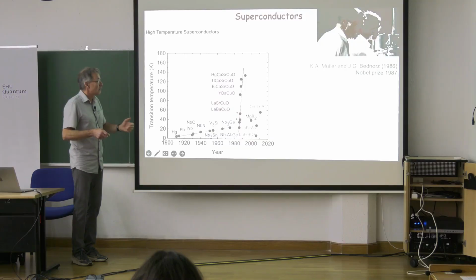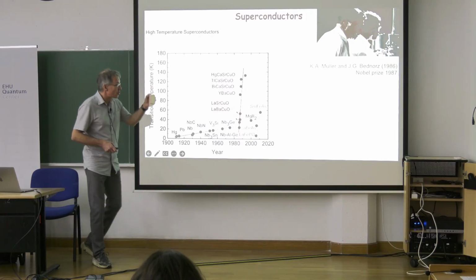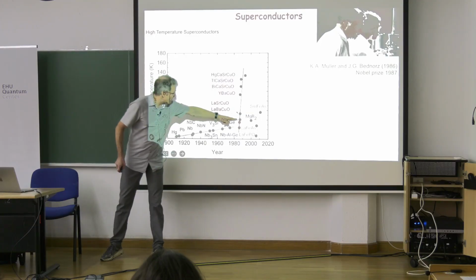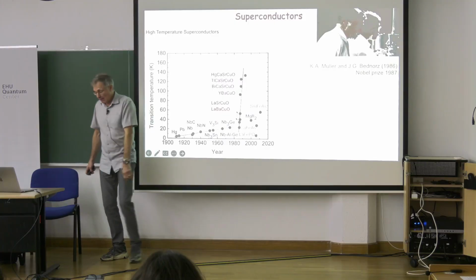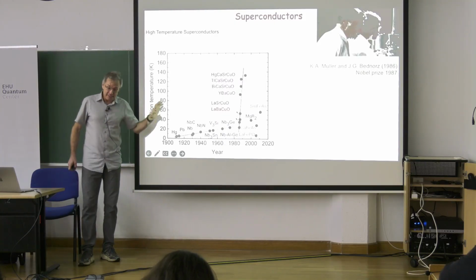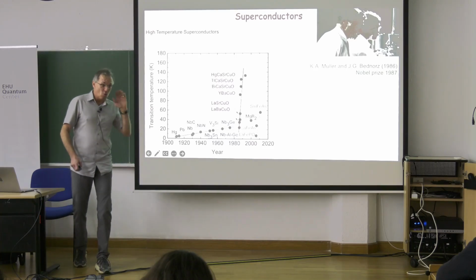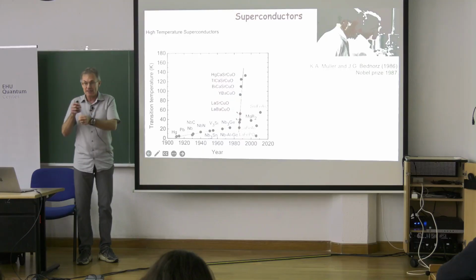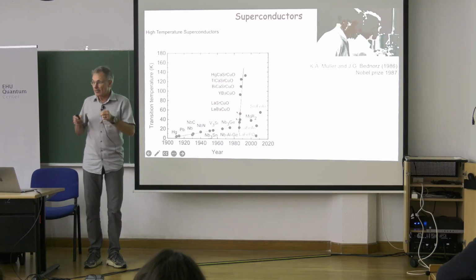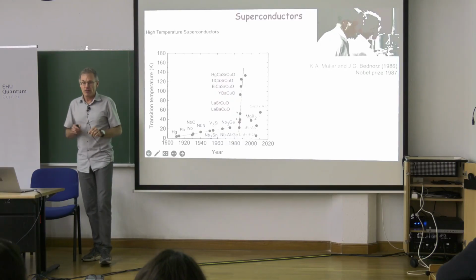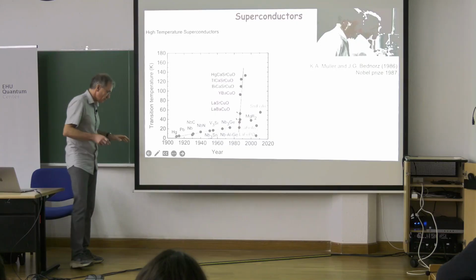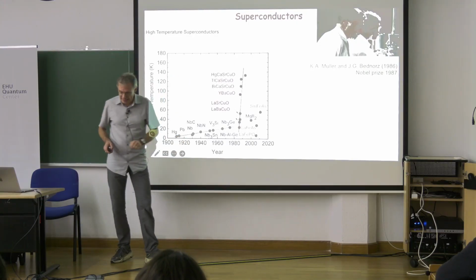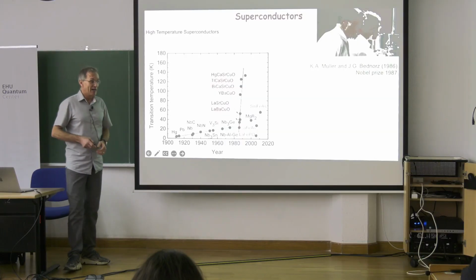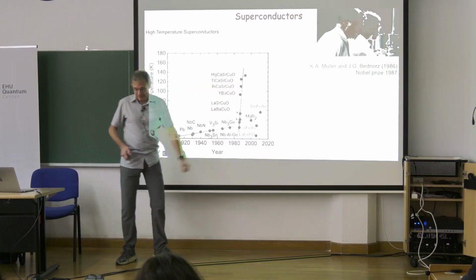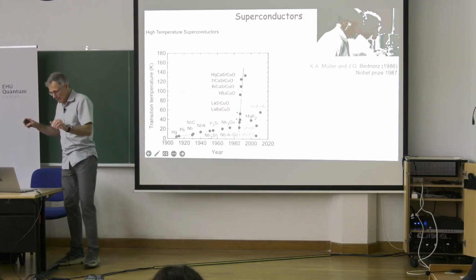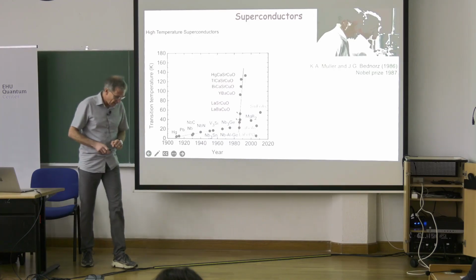And this was a huge surprise when Alex Müller and Georg Bednorz discovered, actually what they discovered was a little bit higher, at 36 Kelvin, a lanthanum compound. Well, they didn't discover it by chance. Alex Müller had studied for decades and tried to find high temperature superconductivity, and he had his own ideas where to look. Most people believed that the ideas were wrong, that he was looking for a black cat in a dark room where the cat was not there, but he found it. It was a huge rise of temperature, and people really got crazy about superconductivity.